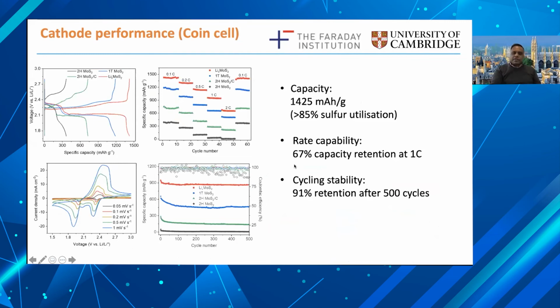So let me show you some of the properties that we achieve from these 1T phase MoS2 cathodes. They're really extraordinary. First, we made some coin cells where we were only testing the properties of the 1T phase. If one looks at the capacity curves, one can see these very nice plateaus. All of these plateaus point to the different polysulfide reactions that happen on the cathode in the lithium sulfur battery. And so we get these very nice characteristics, very good rate performance as well.